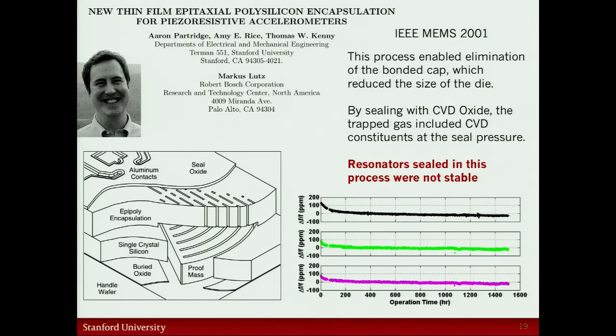So instead of putting a second wafer on top of the first wafer, figuring out how to glue them together, we build up the package by growing layers on top of the silicon wafer based on materials that we had access to. Bosch at the time had developed a process for low-stress, thick polysilicon, the so-called Epi-Poly. We had an Epi reactor in the lab at Stanford, which wasn't designed for this purpose, but could be adapted to do this job. And so we started growing packages by building layers on top of the MEMS technology and seeing what we could do with this.